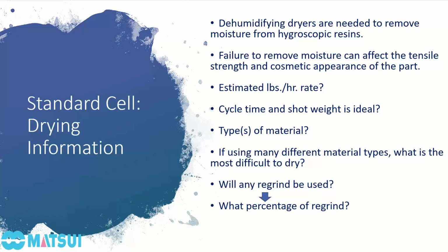concern with regrind is that regrind has a lot of dust and fines, and it also has a lot of miscut shaped material. So it's not in a uniform pellet size, but a lot of miscut pieces. And the dust and fines, as well as the miscut pieces, can impede airflow. So, airflow through the drying hopper is always very important for a dryer. If regrind is impeding that airflow, you might have to dry material for a little bit longer if larger percents of regrind are being used.